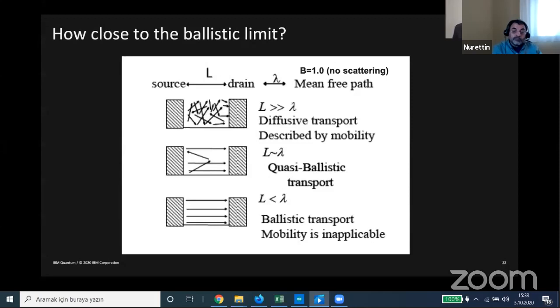Shown here are three regimes of operation. One where the length is much larger than the mean free path, one where the length is roughly equal to the mean free path, and one where the length is less than the mean free path. So when the length is much bigger than the mean free path, we're in a regime of diffusive transport. You have a lot of scattering events between source and drain. So we can describe this with the concept of mobility. So if you double your mobility, essentially you double your current. In the quasi-ballistic transport regime, you only have a few discrete number of scattering events from source to drain, while in the ballistic regime, the carriers just go from source to drain with no collisions whatsoever, so the concept of mobility is inapplicable. So even if we were to boost the strain and get more mobility, we wouldn't see any transistor performance.